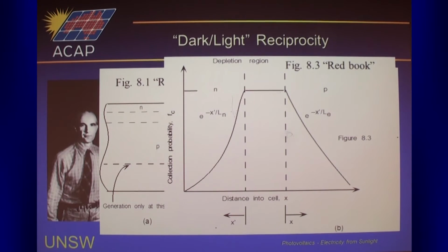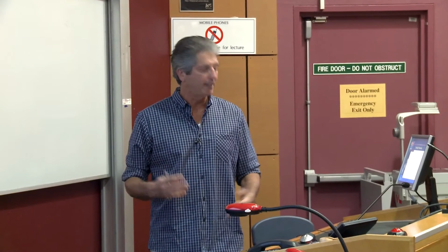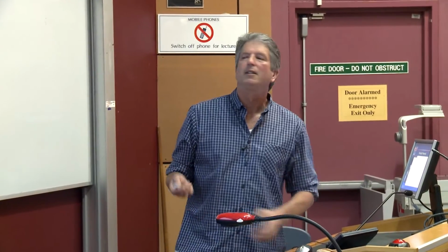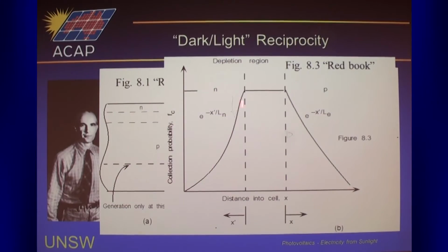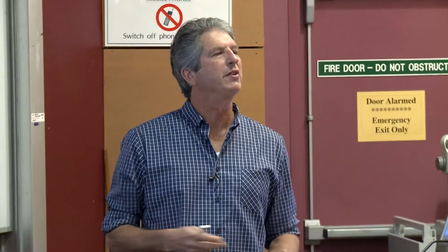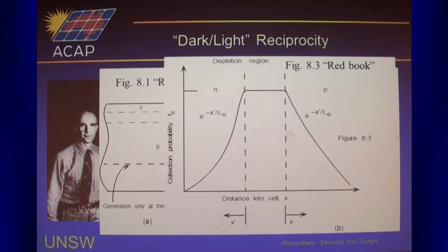If I had been a bit more astute then, we said, wow, that looks pretty much like the decays of the whole of the minority carrier concentrations we saw in some of those earlier overheads. And in fact, it turns out that that's the case. There's a relationship between this decay here and the distribution. This is for a device that's illuminated. There's a relationship between this collection probability and the distributions you get in the device in the dark.